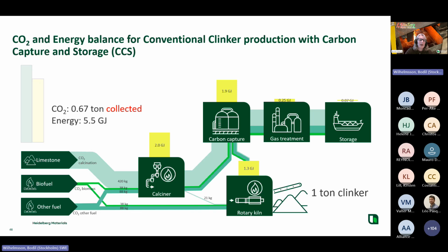And this will then give that we need the same amount of CO2 as in the previous picture. We need to collect that, and with this scheme we do that, but it costs a bit more energy. From 3.3 gigajoule, we now need 5.5 gigajoule to make this happen. But then no CO2 is emitted to the air, which is of course the aim with the whole thing. And the best thing with this is that since it is a post-combustion technique, the quality of the product is unaffected. So it's still the same good quality of the product, even though all the CO2 is removed from the product. But the energy consumption is high.